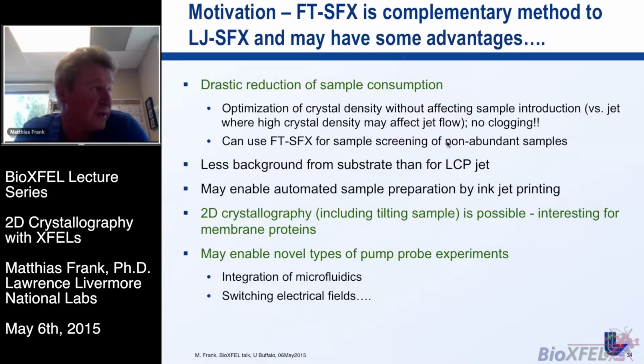You can use a fixed target approach for sample screening. If you have only small amounts of sample, you put them down on a fixed target, you know where they are, and you can do screening to see whether your crystals diffract or not. There's less background from a thin substrate, and when I say thin, I mean like a 30 nanometer membrane of silicon nitride or carbon that's supported by a larger silicon wafer or some other type of wafer. The background from that is much smaller than for LCP. And there are some automated sample preparation techniques that we have been exploring, like inkjet printing, where you can actually put down exactly the right amount of sample.